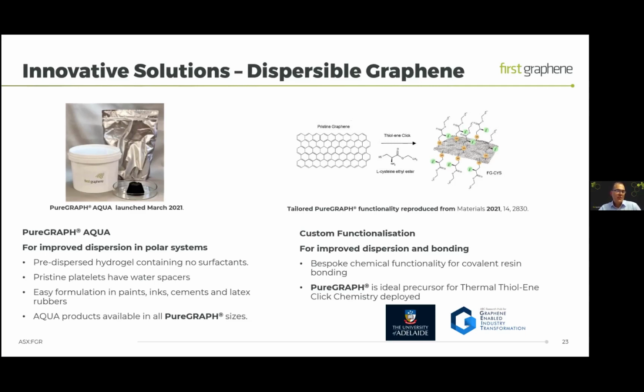In addition to that, we continue to look at functionalization, and our collaborators at the University of Adelaide have just published some really interesting work using PureGraph materials. And they found that the PureGraph platelet is actually an ideal precursor for these functionalization chemistries. And this is because, as I described earlier, PureGraph is a pristine graphene platelet with some oxygen functionality at the platelet edges. So it's ideal for chemistry to functionalize and make the material more compatible. So we're working with the University of Adelaide, and we've got the opportunity to make even further enhanced water-soluble or water-dispersible materials. But what's really interesting about these is the opportunity to make reactive functionalities. So we can actually have graphenes that participate in the curing reactions of rubber systems, for example. So a really, really interesting development.